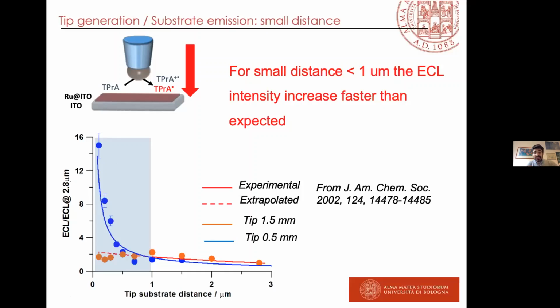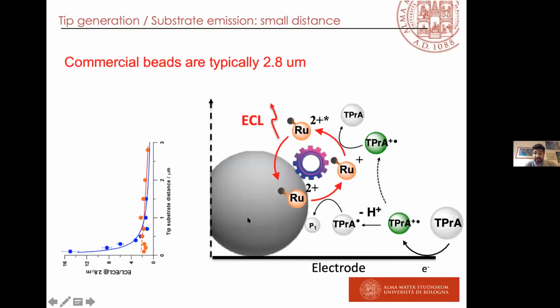Amazing. This means that if we concentrate the ruthenium dye, the ECL emitting dye, at this distance, less than 1 micrometer, so if you concentrate the ruthenium dye in the first micrometer, we can have a higher intensity compared with the long distance. And that's exactly what we did.